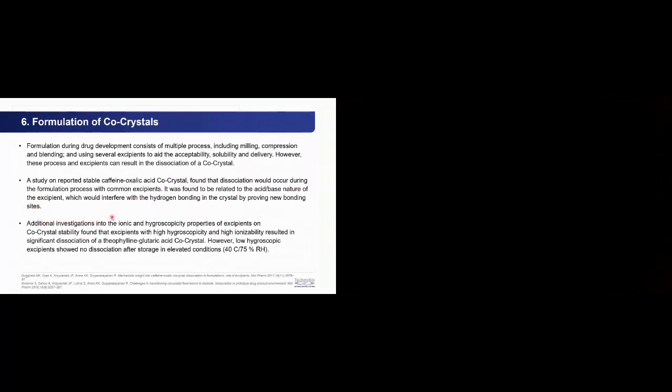Additionally, in a different study of a theophylline glutaric acid co-crystal, they found that a high hygroscopicity and high ionizability resulted in significant dissociation of the co-crystal, where a low hygroscopicity excipient showed no dissociation after being stored at elevated conditions. So it emphasizes the importance of looking at what excipients you are using and what effect that can have on the co-crystal's stability.